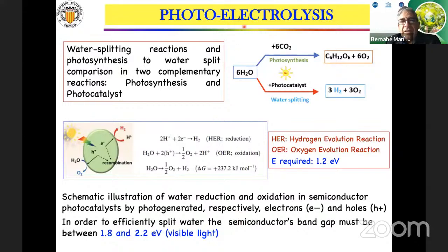For the case of photoelectrolysis, or photolysis, we use some materials where we produce electron-hole pairs, by means of the hydrogen evolution reaction and the oxygen evolution reaction, which are produced at the cathode and the anode. So we split the water molecule into oxygen and hydrogen. To do that, the energy required for each molecule is a photon of 1.2 electron volts.